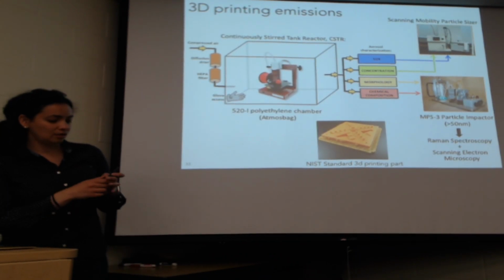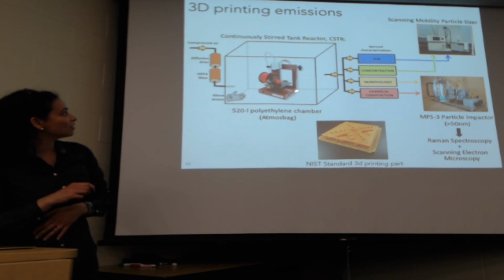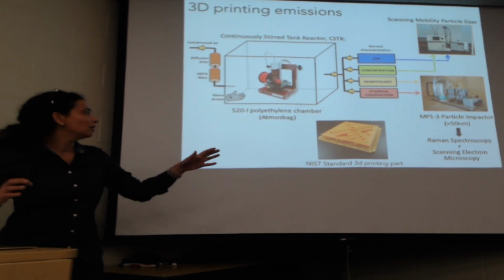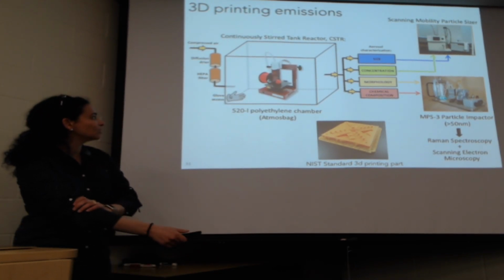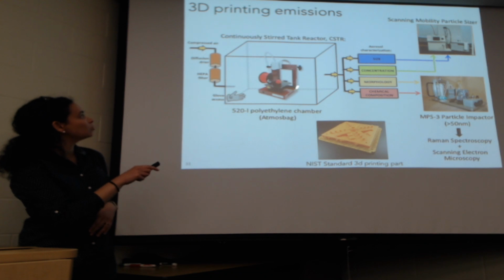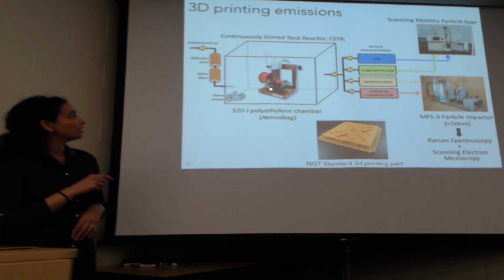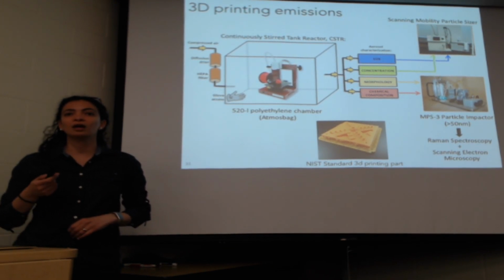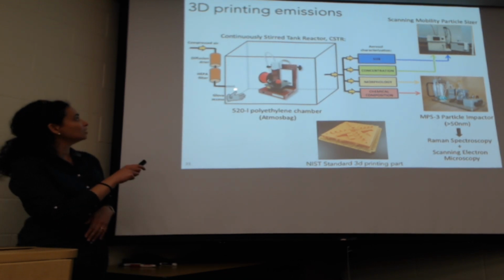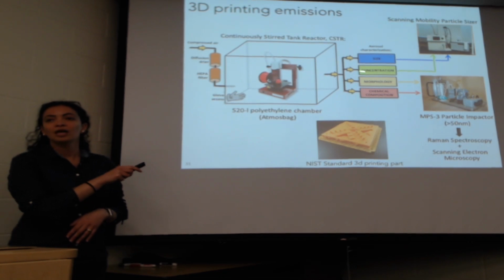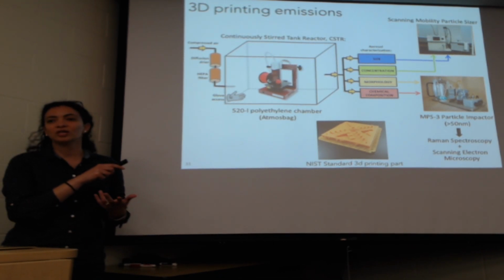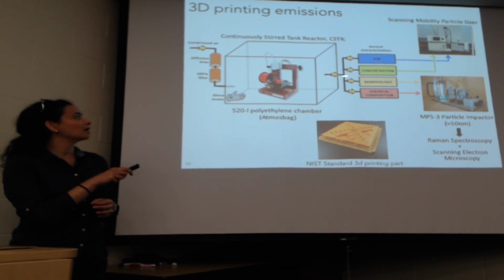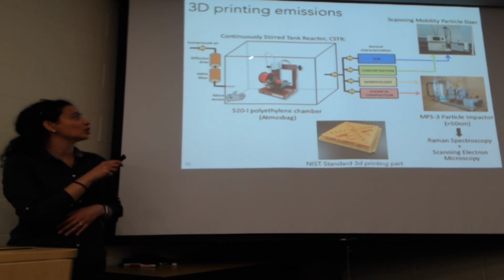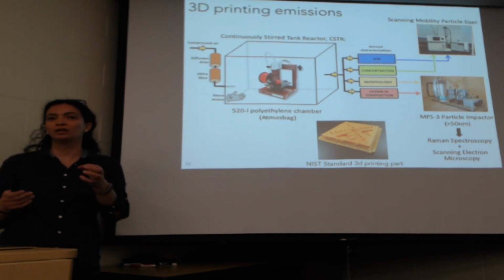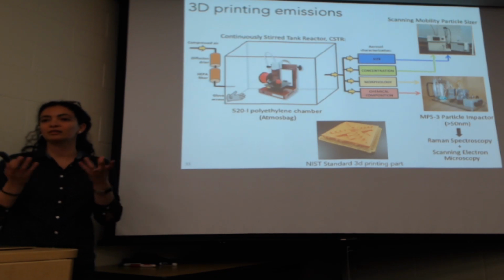So to do that, we did a controlled chamber study. Our chamber is basically a glorified bag made of polyethylene, about half a cubic meter. It has some glove access, so you can operate the 3D printer inside it. And we operate this chamber as what we call a continuously stirred tank reactor. This is important so that we can model emissions later on. It means that we know what's coming in, we know there's something going on inside, we know what's coming out. And if we measure what's coming out in terms of concentration, we assume that concentration is representative of anywhere inside the chamber. So the chamber is a mixed tank. Well, the printer itself has a fan, so we assume that's complete mixture.